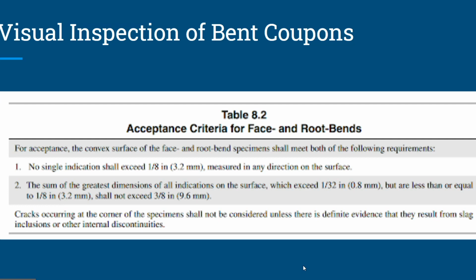Now, this is where there's a slight difference between AWS criteria for the SENSE program and AWS D1.1. D1.1 goes into more detail about corner cracks. If it's bigger than a 1/4 inch and we still don't see any evidence of any discontinuity causing that crack, then we can replace it with a different sample and bend that. They don't get into that in the SENSE program, but that is something that I still do. If we get a big crack in there, I'll just replace it with one of their other samples. Unless that crack is caused by a discontinuity, then it automatically fails. It doesn't matter if it's on a corner.